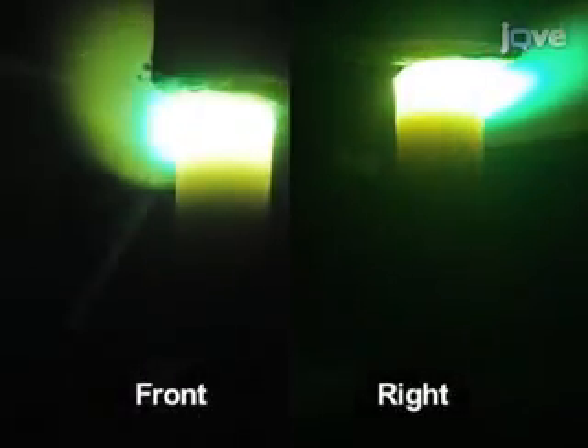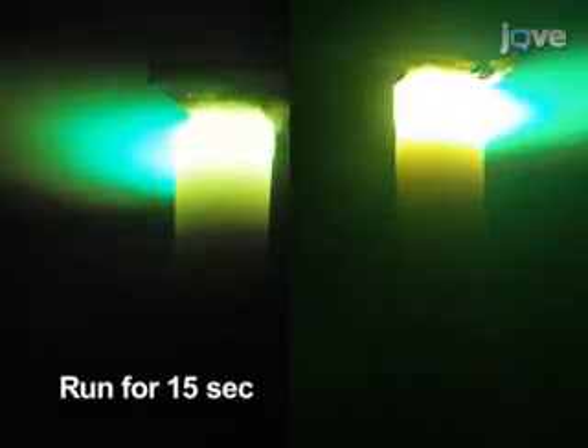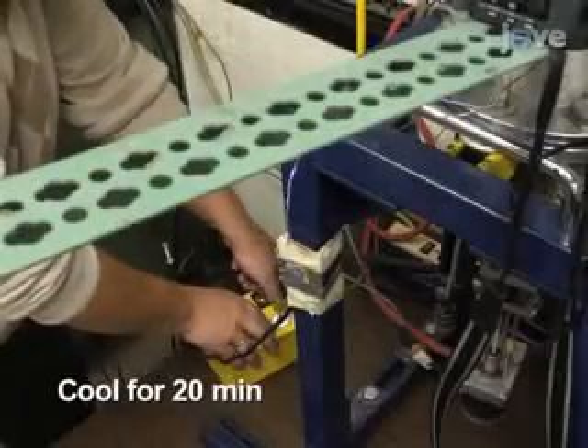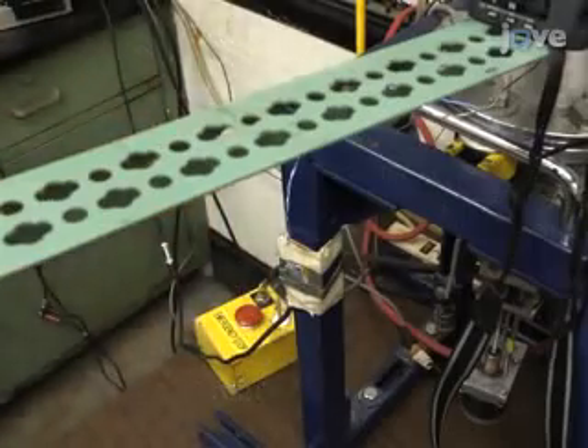Record the real-time values of arc current, arc voltage, and chamber pressure for post-experimental analysis. Start the video of arcing from the right and front viewports simultaneously with 2 digital cameras. Run the arc for 15 seconds. Cool down the chamber by natural convection for at least 20 minutes.